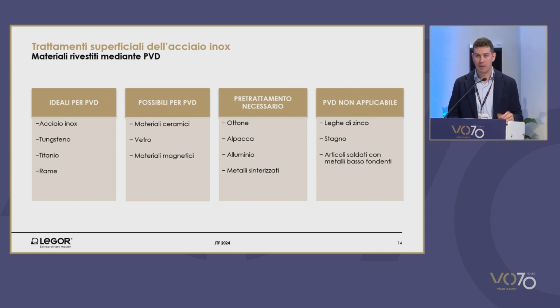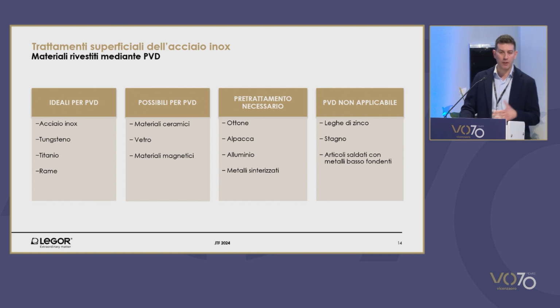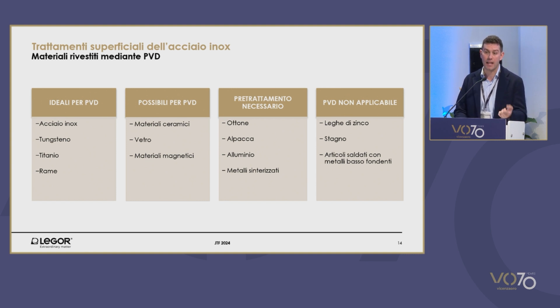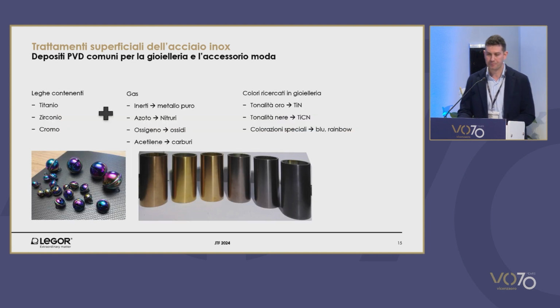Deposition can also be performed on magnetic materials, ceramic and glass, but it is more difficult. Other materials, such as brass, alpaca, aluminum, and sintered materials, require a pre-treatment. Oftentimes, electric deposition is resorted to before. Low-melting alloys cannot be treated with PVD, as in the case of zinc-tin alloys, or those with a soldering, including some of the elements that I've just quoted.